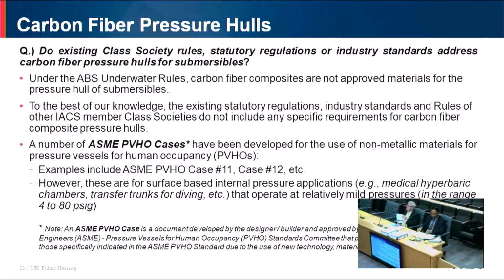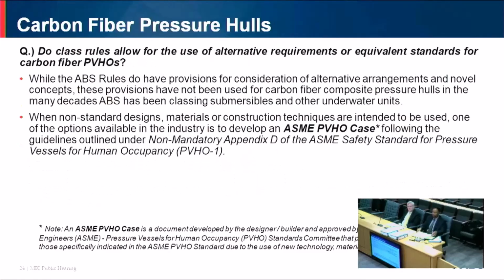Then case number 12 was a non-metallic portable hyperbaric stretcher, and the material used was a liquid crystal polymer tube which was enclosed in polyurethane and which was then coated with nylon. And the maximum pressure for this application was in the range of 33 to 75 psig. So all of these are for internal pressure applications, and they are for very mild pressures as compared to the pressure at a depth of 4,000 meters seawater. Okay, next.